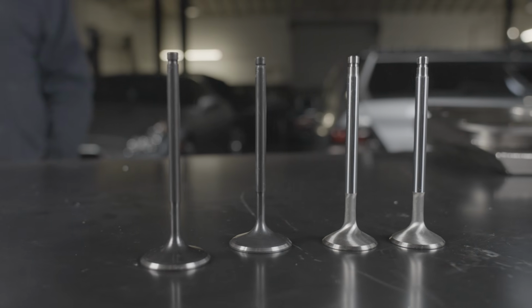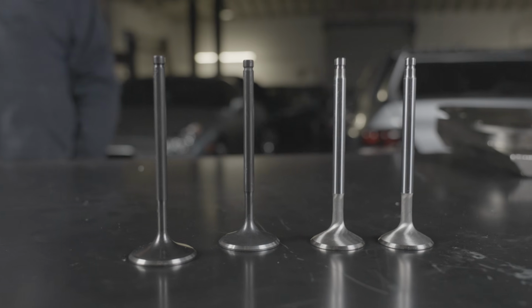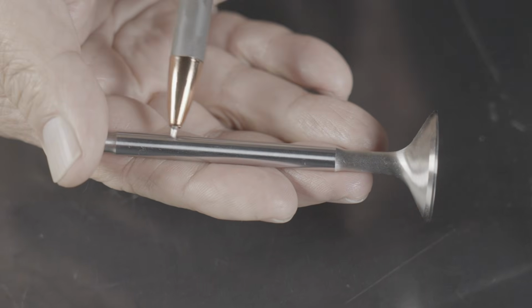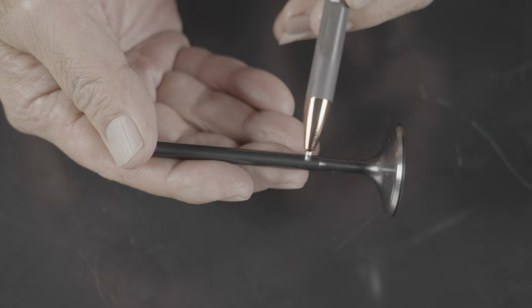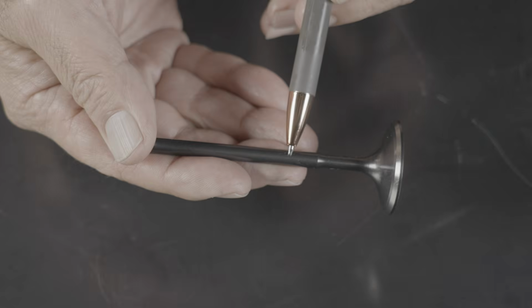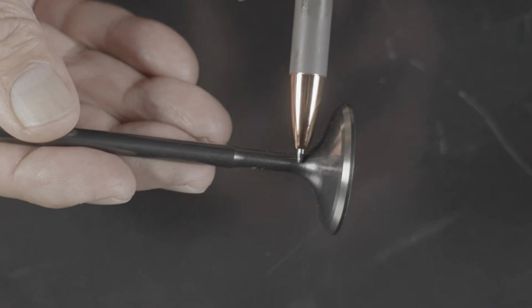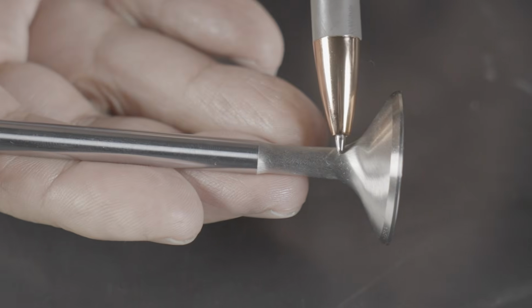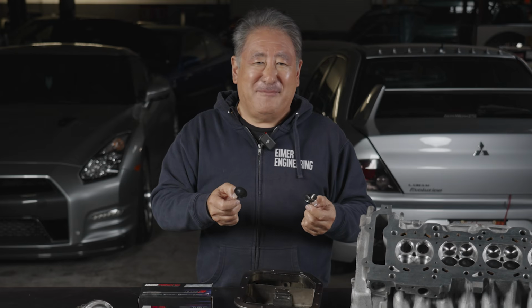So we went to SuperTech oversized valves. Now these valves are 1 millimeter oversized from stock. The exhaust valve is Inconel, which is a super high heat resistant alloy, really important to use on turbo engines. The intake is a stainless that's black nitride. Nitriding is a really hard, slippery, heat resistant surface treatment. So that really helps the wear and longevity of the valve. When you look at the SuperTech valves, you can see that they have a reduced stem diameter in the area right under the head. Now, this actually helps flow quite a bit.